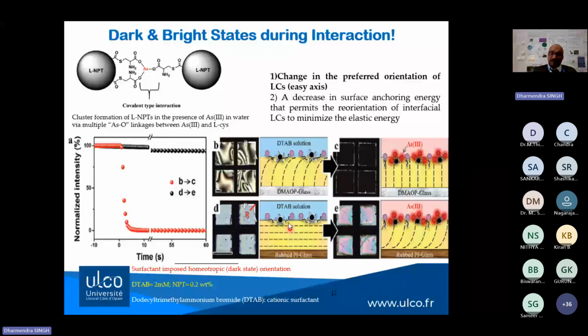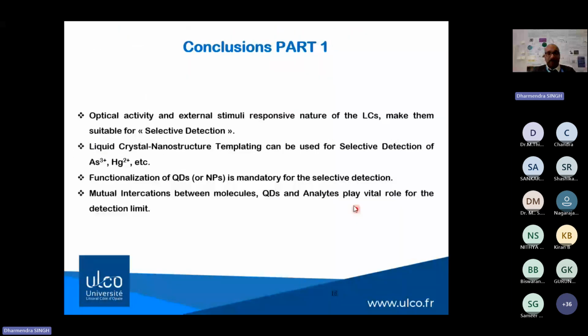And when you still use this arsenic molecule, there is no change at all. So when there is no change at all, even after the presence of arsenic ions, then we realize that basically the change in the preferred orientation of the LC axis is the responsible mechanism for this change in optical texture of the liquid crystal materials. So, okay, this is the conclusion of part one.